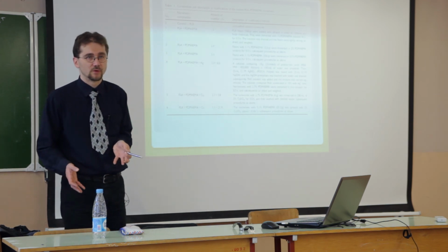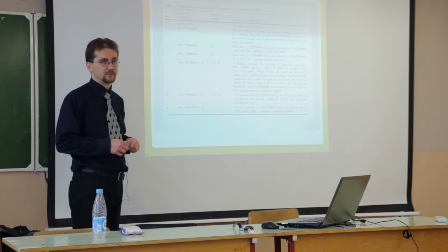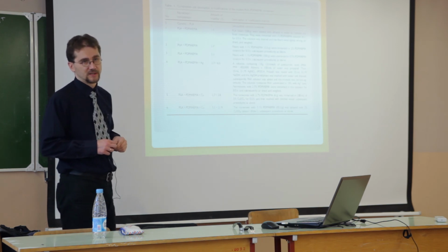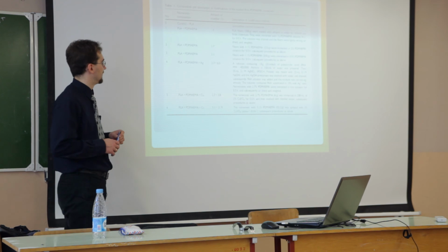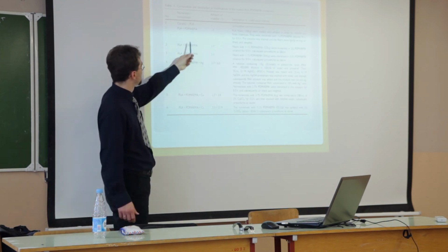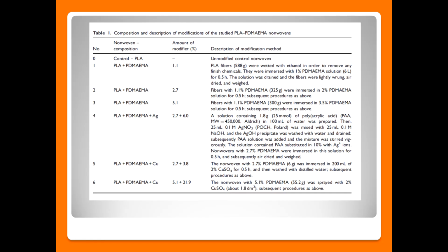But we don't want to use a surface with soluble material on it. So we deposited different amounts of that polymer: about 1%, about 3%, and about 5%.